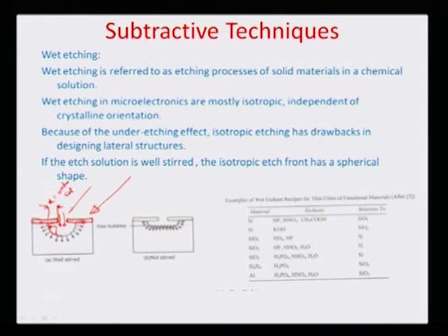If the etching was not homogeneous, as illustrated here, the etching may be a little more directional. In this case, you can see the etch rates are more towards the side, so lateral etching is more, and it would result in different shapes based on the directionality of the etching. Typically, if you had a very well stirred solution, where whatever is coming out goes away from this etch window, it would result in a homogeneous profile like this. If you do not have a well stirred solution, it would rather result in this, because the concentration of atoms coming out of the material would be higher here, and diffusional restrictions would prevent further etchant from moving away, so the rate in the vertical direction would be reduced in comparison to the horizontal direction.